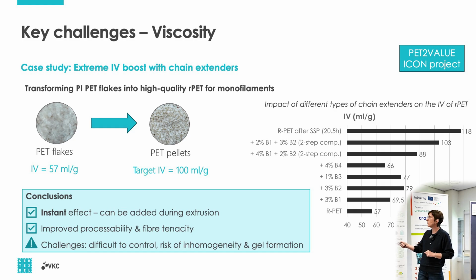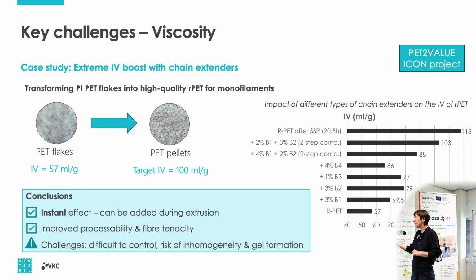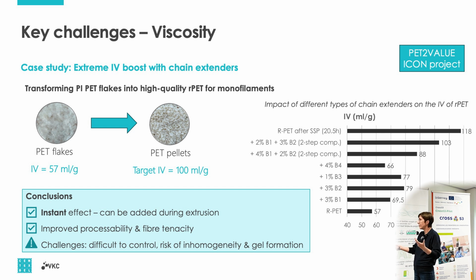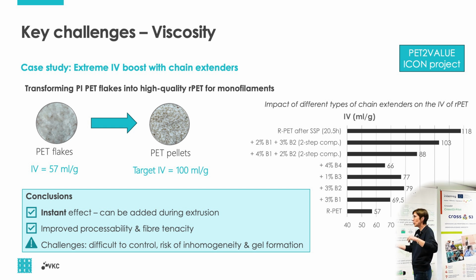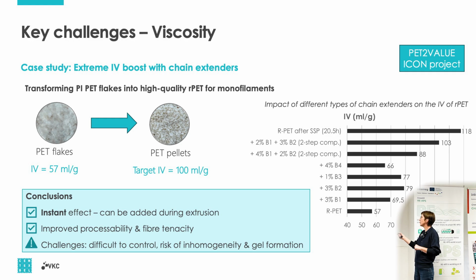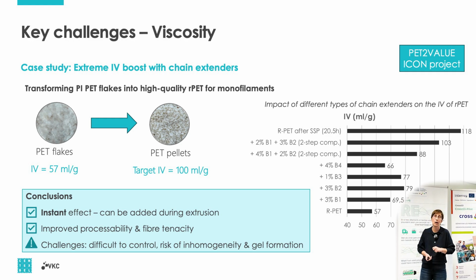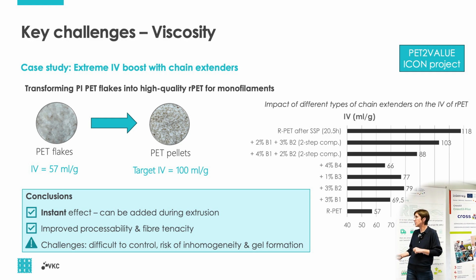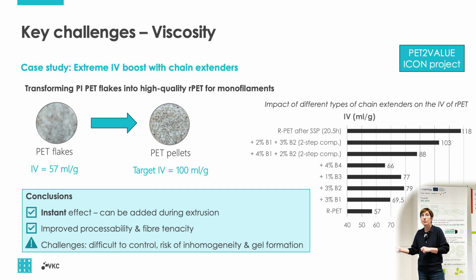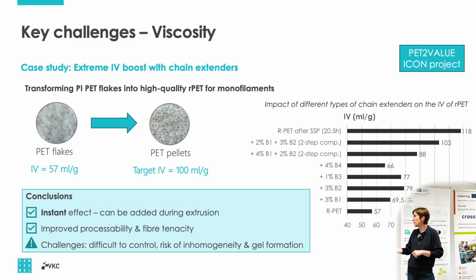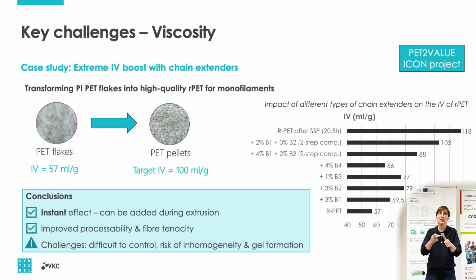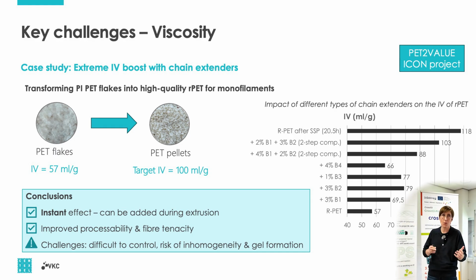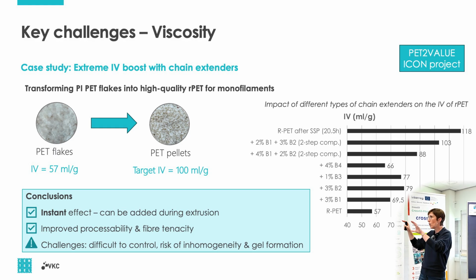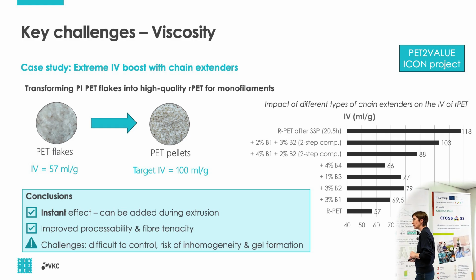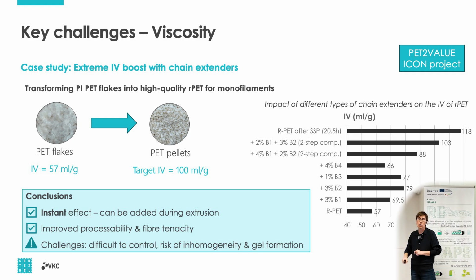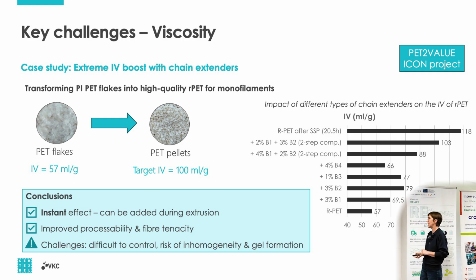So here we worked with different combinations of additives, and you could see that we started very low, suitable for multifilament extrusion, not suitable for high tenacity, and with different chain extenders we were able to increase the IV value. So yes, we can improve processability and fiber tenacity. Yes, we have some effect. The challenges, of course, like I said, it's an additional cost, but it's also sometimes difficult to control because you don't know how many of those chains you're really extending, and there's still some risk of inhomogeneity and gel formations to be taken into account.